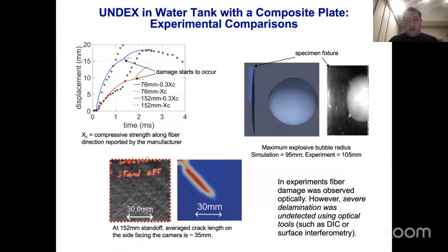Okay. Here's some experimental validation, right? The maximum size of the explosive bubble is recorded to be about 100 millimeters, and we're seeing that in the calculations, right? Our experimental colleagues had a DIC system set up where they're tracking the displacement of the center point of the composite plate, and we're doing very well at the early stages, right? And then we undershoot.